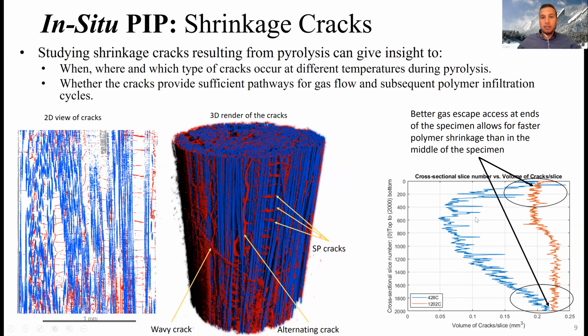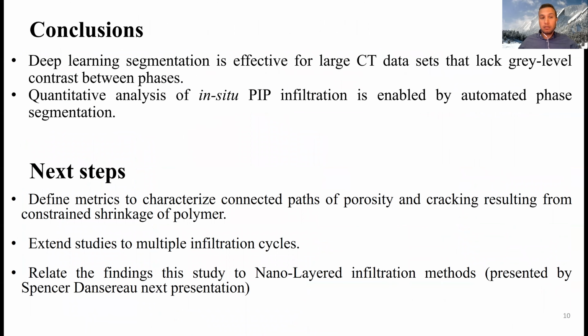So with all of these studies, there is still a lot more analysis that we need to push. But so far, this method of segmentation has been effective for large CT data sets. And not only that, it allows for feasible quantitative analysis on these images. A big next step for us is being able to identify or define metrics to characterize these connected pathways of porosity and cracking resulting from shrinkage of the polymer. And once we have these metrics, we would like to extend these studies to looking at images with multiple infiltration cycles. After that, it will be very interesting to link this work to what Spencer is presenting next.